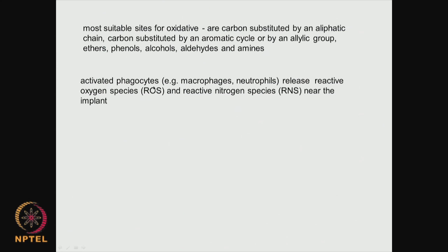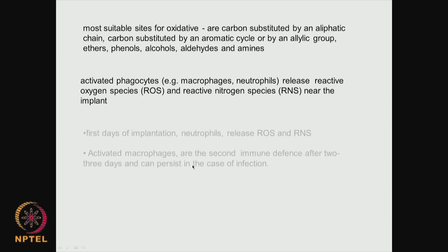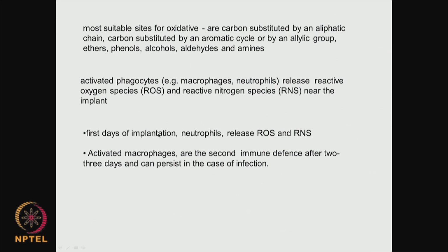So, activated phagocytes, that means macrophages, neutrophils, release reactive oxygen species. These activated phagocytes inside the human body, and reactive nitrogen species near the implant, because they start attacking the implant, because the implant is seen as a foreign body. So, they release reactive oxygen species and reactive nitrogen species. So, first day of implantation, almost 24 hours, 36 hours, neutrophils are released, and after a longer time macrophages are released actually. So, the first day of implantation neutrophils are released, so they release ROS and reactive nitrogen species.